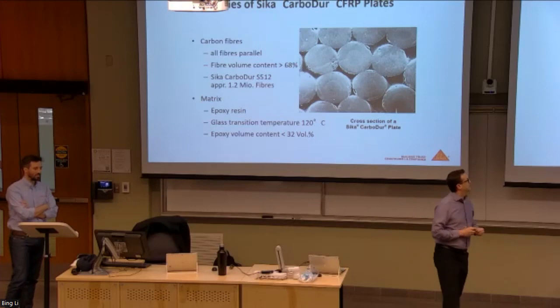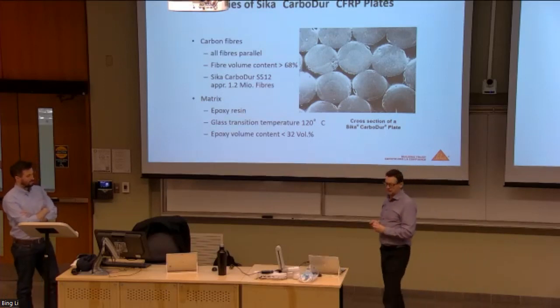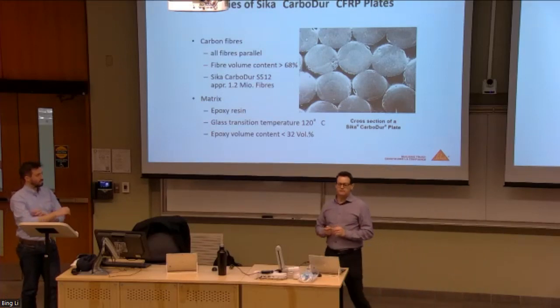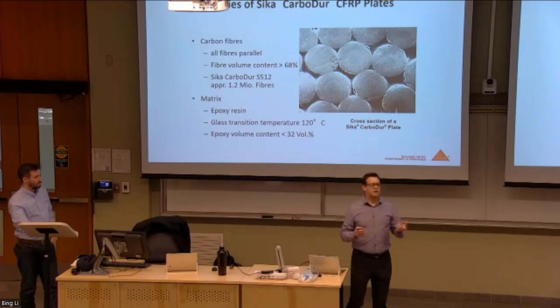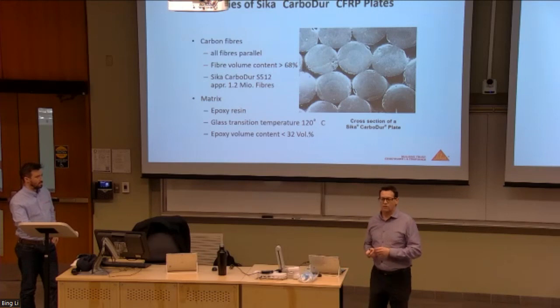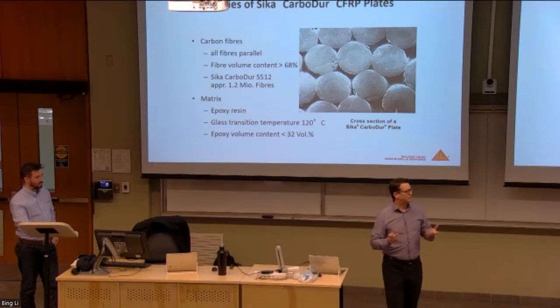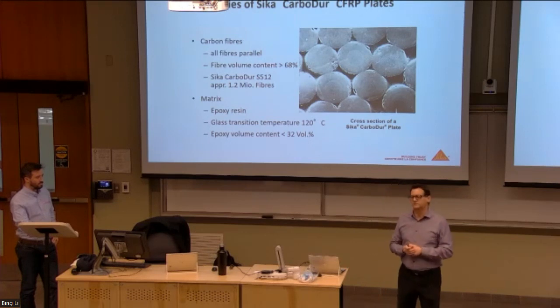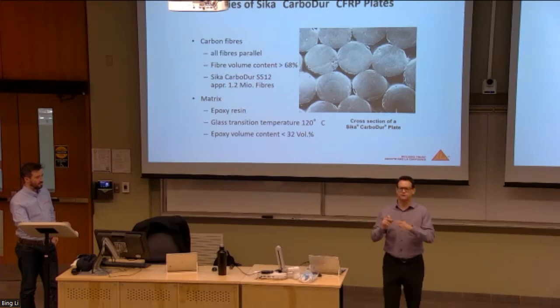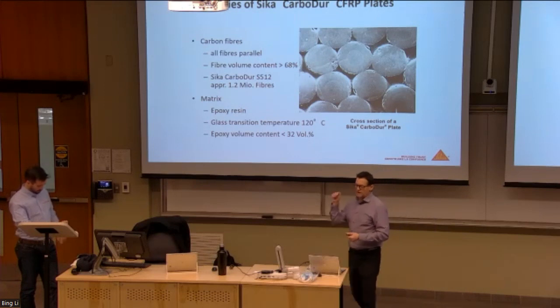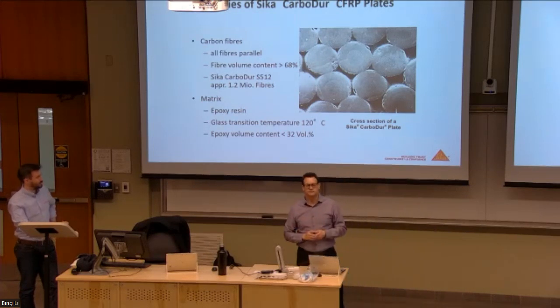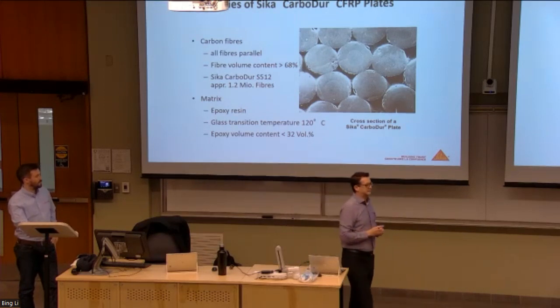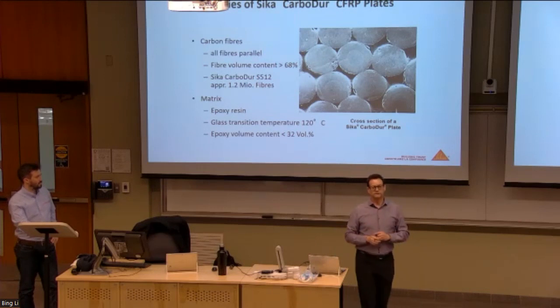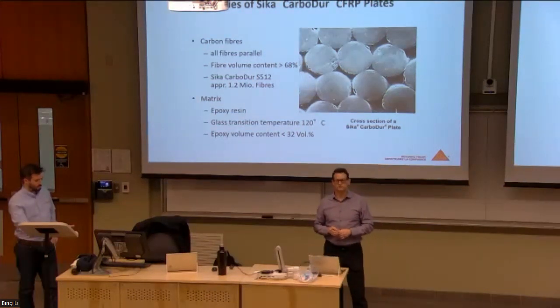Under a microscope, these fibers are running in parallel, and there's literally millions of them in a profile that might be 1.2 millimeters in thickness and, say, 100 millimeters in width. So you could have 1.2 million individual strands of these fibers running in that geometric shape. You line all those up together, you encase this in an epoxy bath, and at the end of the day, you're giving yourself an extremely high flexural strength product.